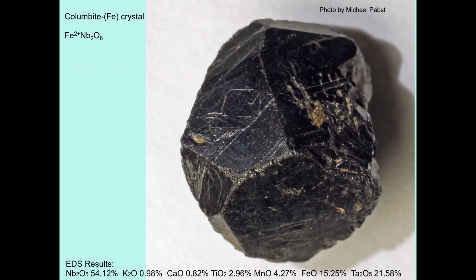One of the purposes of the Rutherford Mine research was to establish a greater degree of clarity with regard to the columbite-tantalite series of minerals. The analysis of this sample shows that indeed, niobium and tantalum were both present, with niobium being the dominant element. In the early days of collecting at the Rutherford Mine, this mineral was identified as tantalite. In later years, specimens were identified as examples of columbite-tantalite, a term still used in the excavation of this strategic mineral. However, the correct species name for the samples found in the Rutherford pegmatite is columbite-Fe, with the EDS test results properly reflecting the greater presence of niobium as compared to tantalum, as well as a significant amount of constituent iron. Next slide.